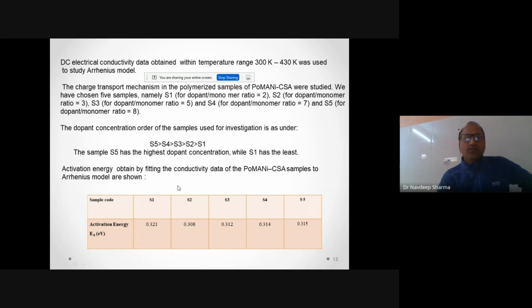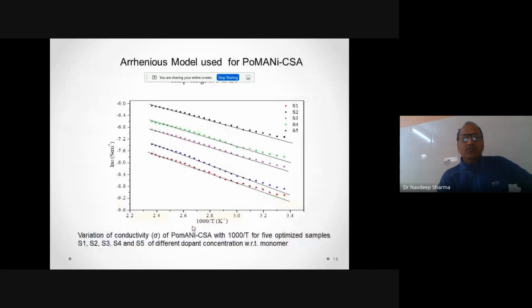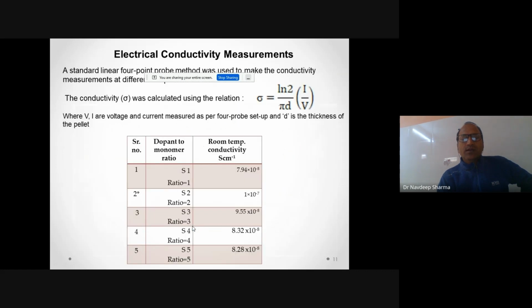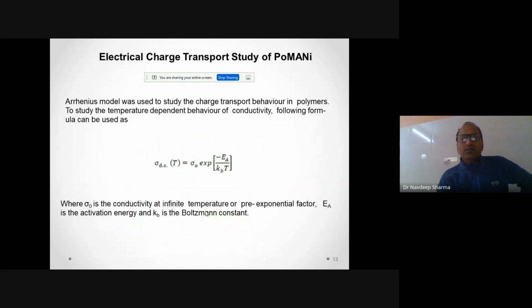And the activation energy for sample 2 is found to be very low, that is 0.308, as compared to the other samples. So this 0.308 activation energy is less in this case. It means that the conductivity is found to be better in this sample S2 ratio, because the charge requires less